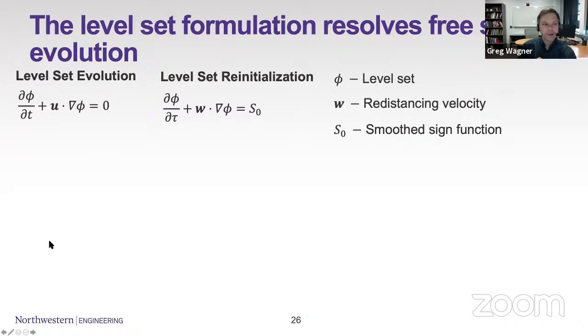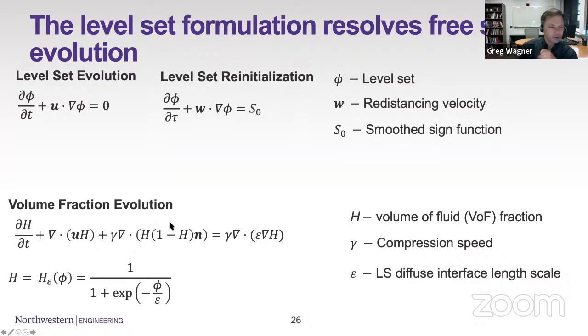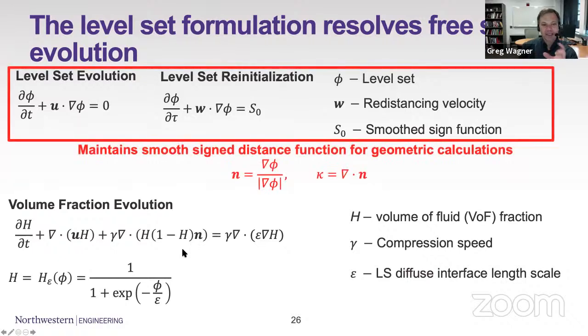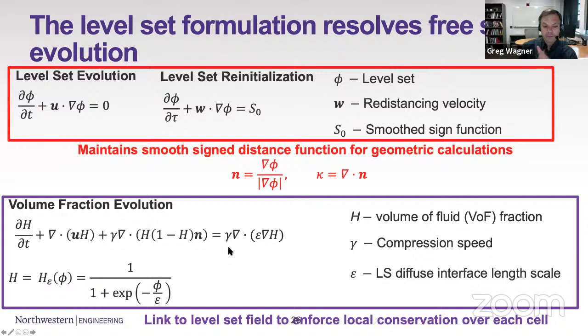We're tracking the moving interface using a level set formulation. I want to keep an eye on my time a little bit to make sure I don't fall too far behind. And we're coupling that in order to well conserve mass. We're coupling this to a volume fraction evolution equation that, taken together with our level set, allows us to improve the mass conservation or the mass losses that you often get in a level set formulation. So the level set itself we're using to maintain a signed distance function, and to be able in particular to compute normal vectors, which is hard to do from a volume fraction equation. The volume fraction evolution equation is then solved separately, and that's what's getting used to actually enforce the local conservation.